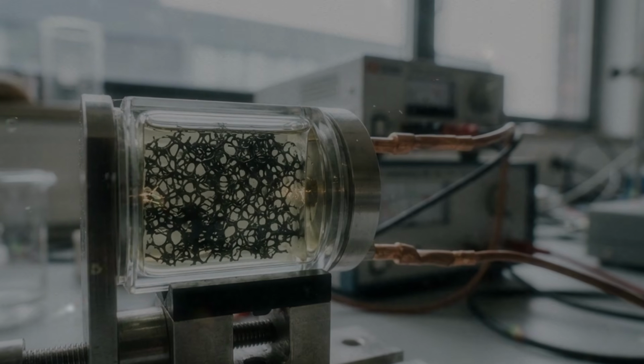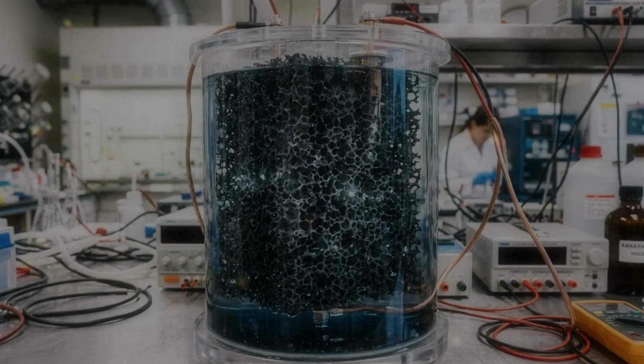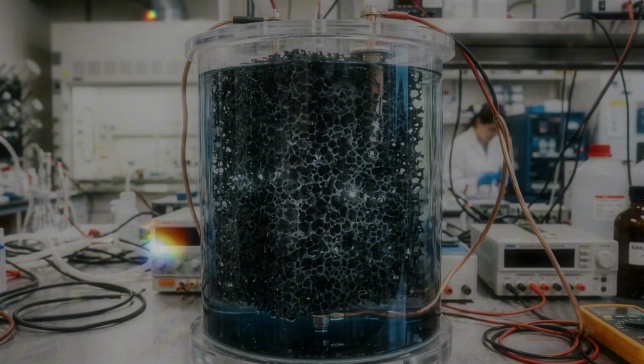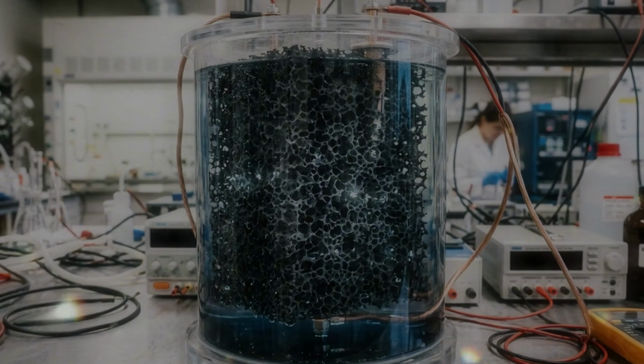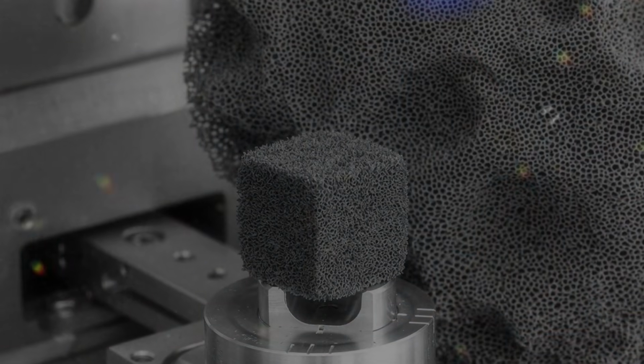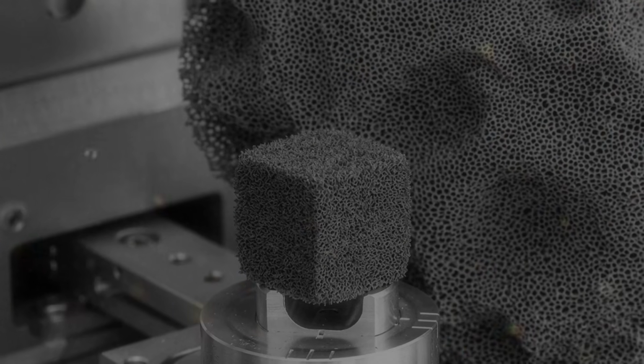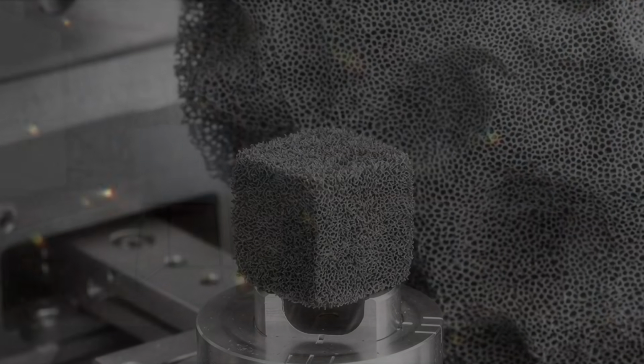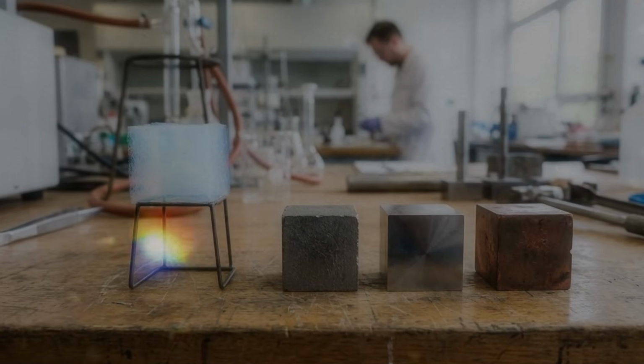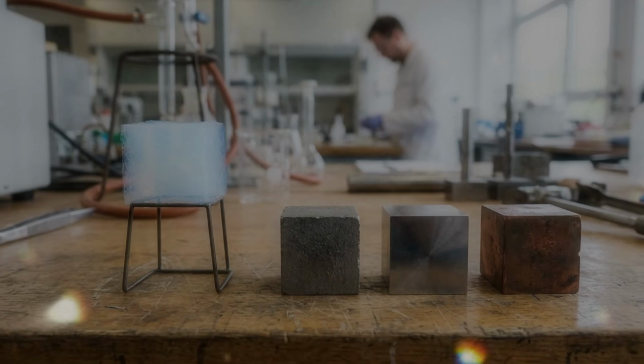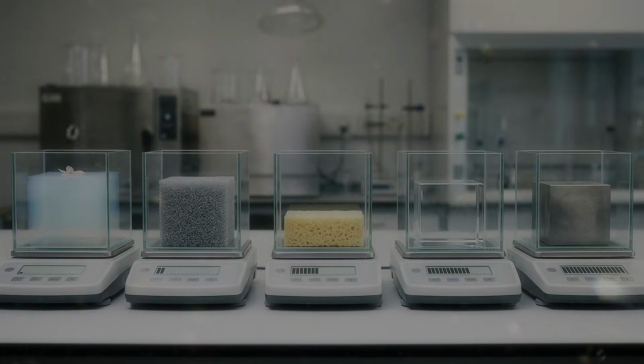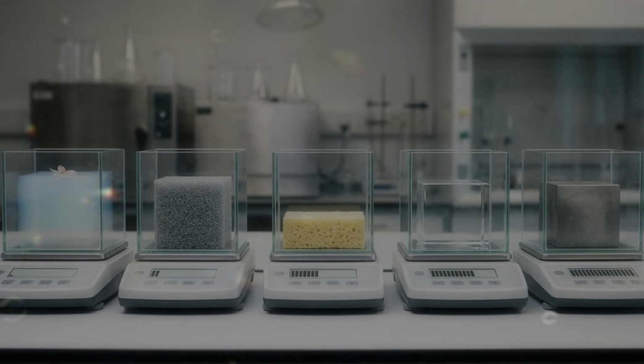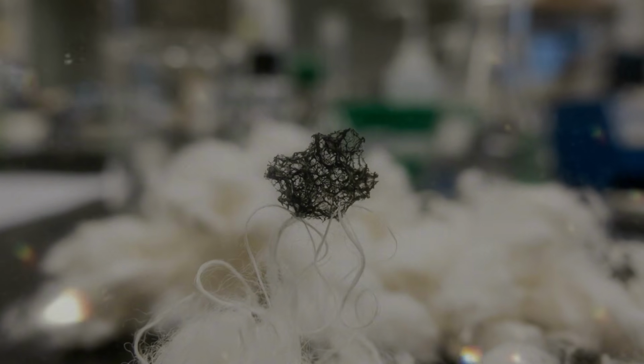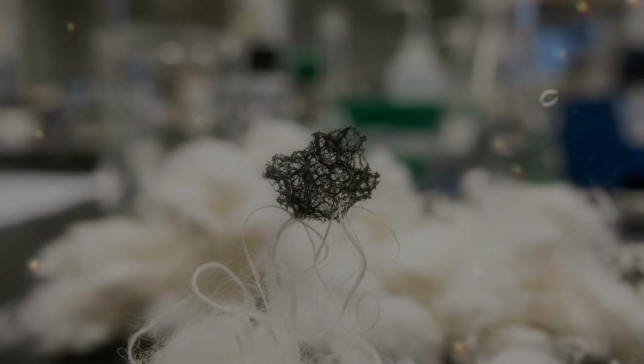Traditional foams often require conductive particles to be added. Aerographene begins with a carbon framework that can already carry charge, provided the sheets are well connected and sufficiently reduced. That combination of low mass, open volume, resilience and conductivity is rare. A metal foam conducts electricity and survives handling, but it is heavier. A polymer foam is light and flexible, but usually does not conduct well. A brittle carbon structure conducts, but may not recover after compression. Aerographene attempts to combine parts of all three.